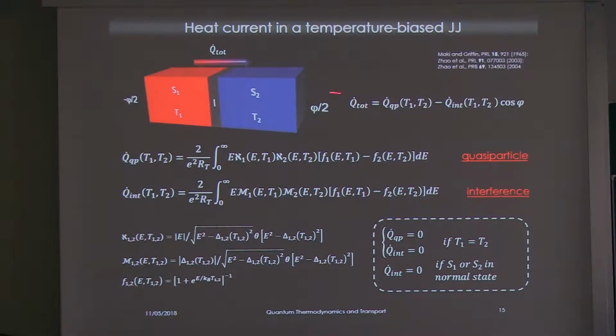If you write down the heat current flowing in a temperature biased Josephson junction, we call the heat current Q dot total. We have two different temperatures, and it's composed of two parts. One is the quasi-particle part, the conventional part, which just depends on the temperature of the two objects. And then there is one additional part that is a phase-dependent part. The phase-dependent part has a minus, which is typical of a tunnel junction. If we had a transparent weak link, there would be a plus and a much more complicated expression as a function of the phase. For a tunnel junction, it's very simple because the phase-dependent part depends on the cosine. So you have a phase-independent part and then a phase-dependent part, whose amplitude can be factorized in this way, superimposed on top of the phase-independent part.